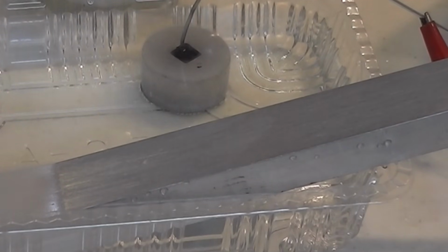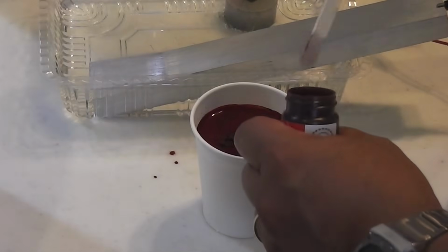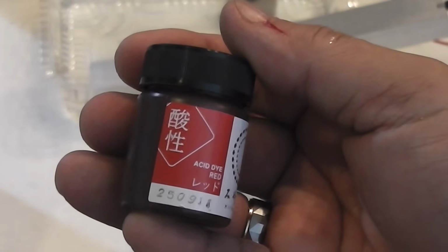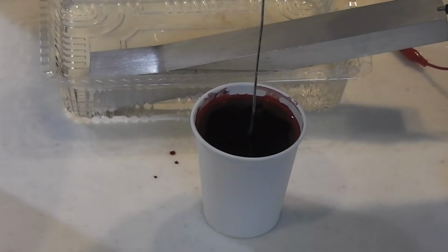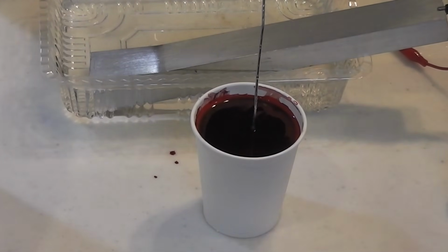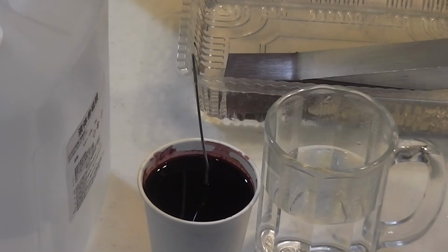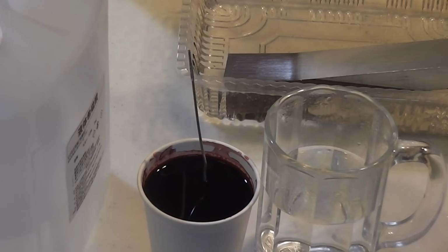After 30 minutes, the anodizing process is complete. The oxide layer is now fully formed, but the pores are still open. That makes this the perfect time to add color. I prepare the dye by dissolving powdered dye in warm water until the solution is completely mixed. The anodized aluminium is then immersed in the dye for approximately 3 minutes. The dye molecules travel deep into the micropores, almost like water soaking into a sponge. At this point, the color is inside the oxide layer, but it isn't permanently locked in yet.